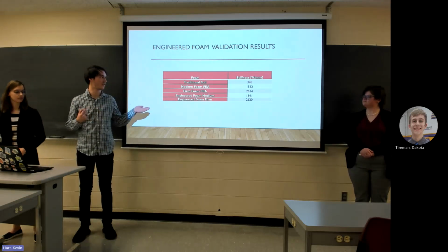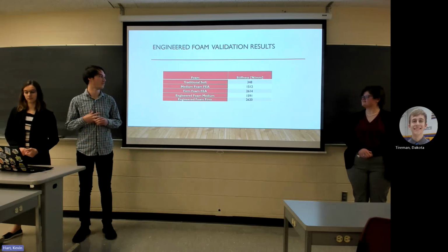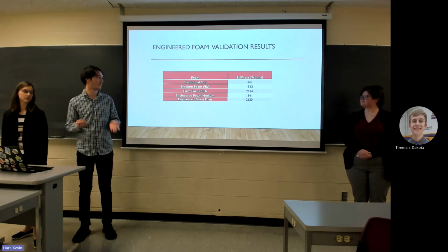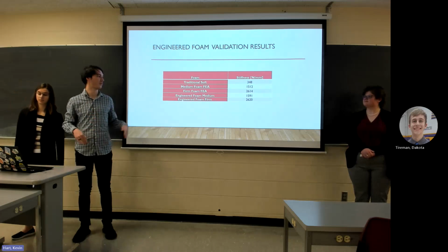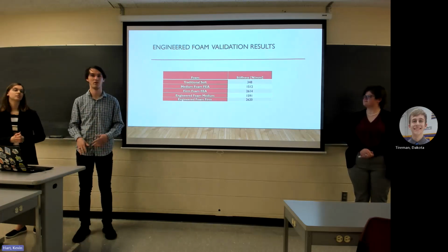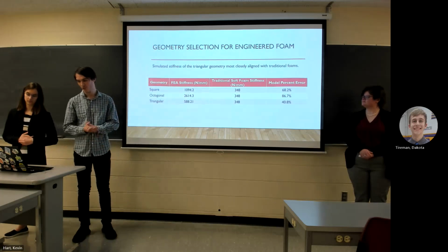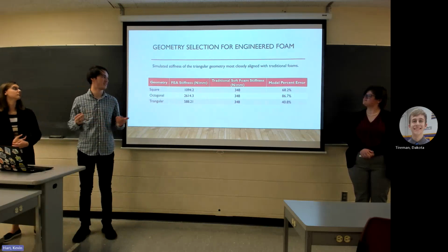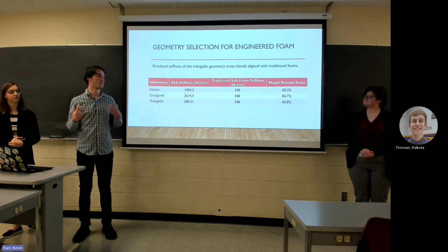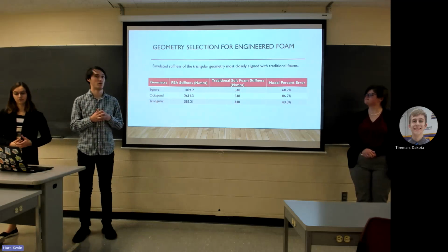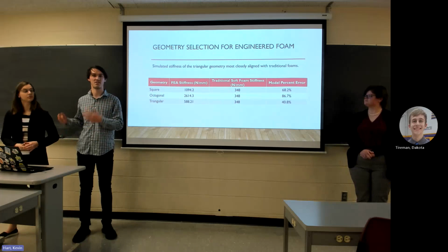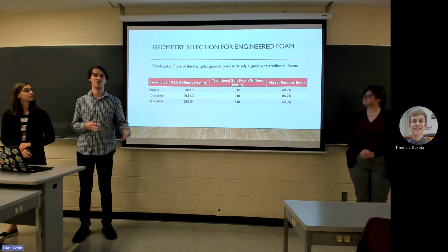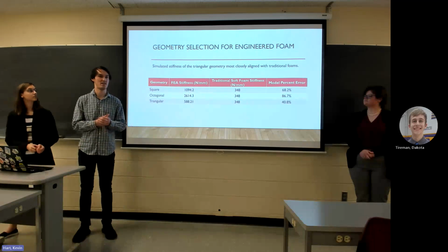And so our actual results here gave us, you know, the medium foam was about 1512 newtons per millimeter. In our FEA, the firm foam was 2614, and then comparing these to those that are actually printed out, we got 1591 with the medium and 2620 with the firm. So we knew that we're in the general ballpark. So as I previously stated, obviously we're still way above with those two, the stiffnesses of where it needs to physically be. So our next step was to look at running stiffness tests in the FEA on different geometries to see how they would actually behave and react.